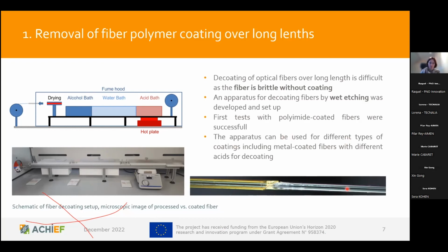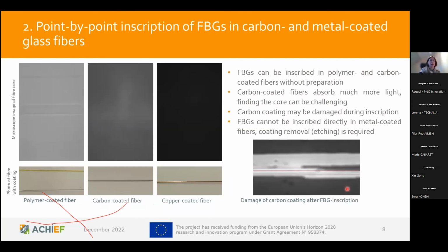In the next step, we wanted to test the FBG inscription. That's a standardized procedure at our company. However, we were not sure if that also would work if we directly would try to write into the fibers. You see here, for example, microscope images of the polymer coated fiber, a carbon coated fiber, and a metal coated fiber.